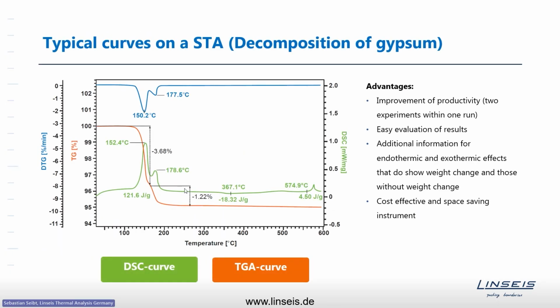The resulting signal that is typically recorded looks like this. That example shows the decomposition of a gypsum sample. The orange curve here is the temperature-dependent mass change of the sample, and you see at a certain temperature, somewhere between 100 and 200 centigrade, there's a two-step mass loss, which is the loss of water in that case. This is typically what a TGA shows.